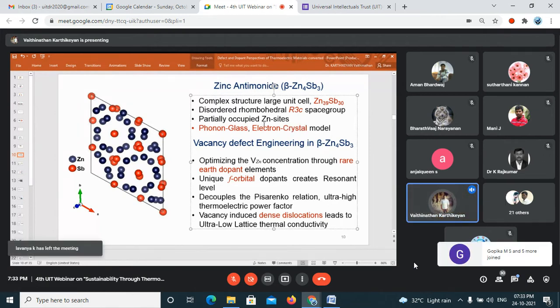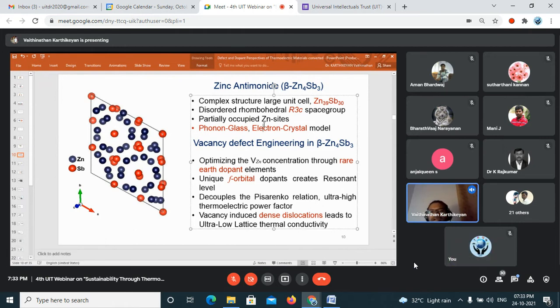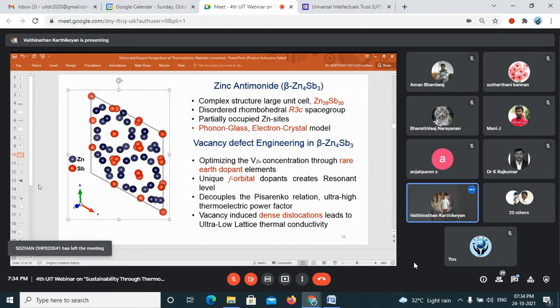Like a crystal for electrons means crystal in the sense of defect-free, a perfect metal, an atomically aligned metal layer to conduct perfectly, giving good, high electrical conductivity. That's what this model means. And here, even though this material possesses this property, its electrical conductivity is very low compared to the conventional materials. So what we try to do is remove a zinc atom, the blue one, from the unit cell. Make it zinc 38, and that's called a zinc vacancy defect.